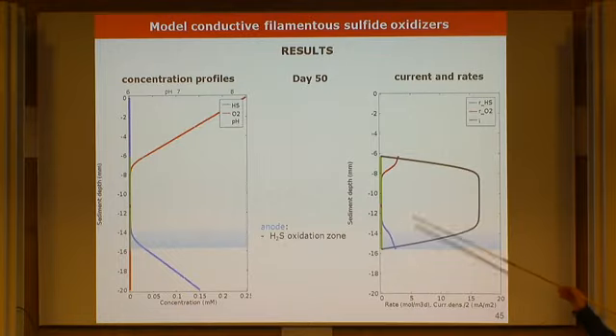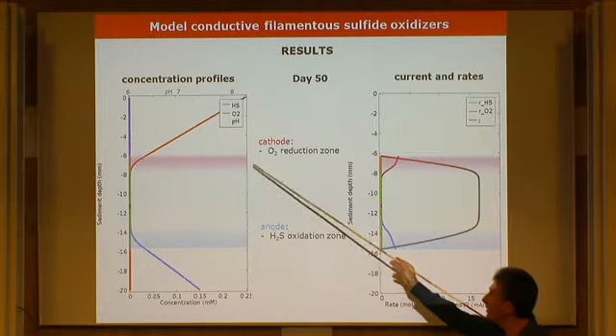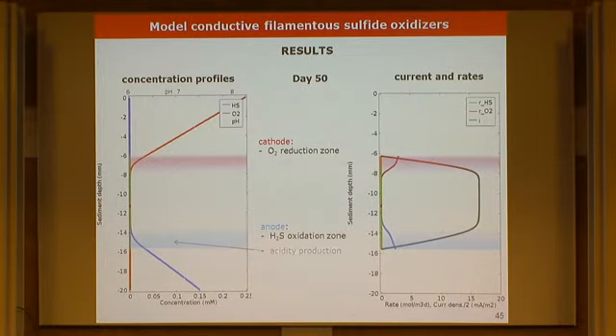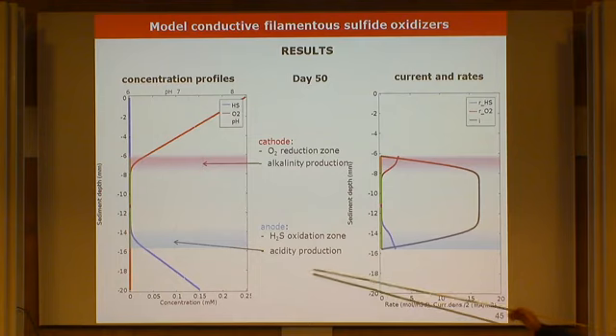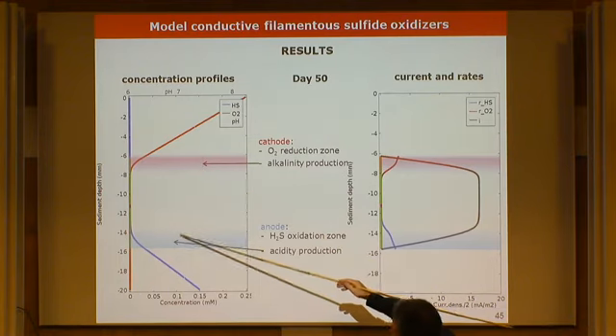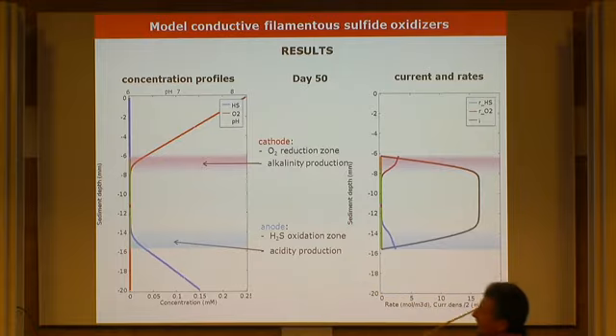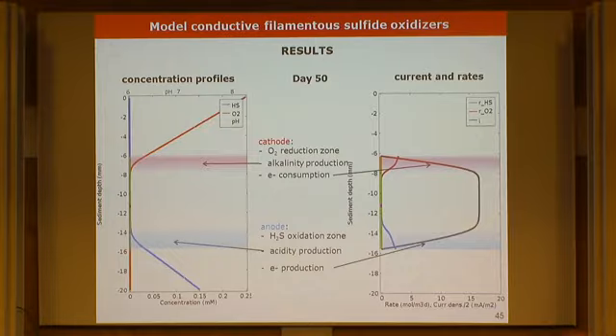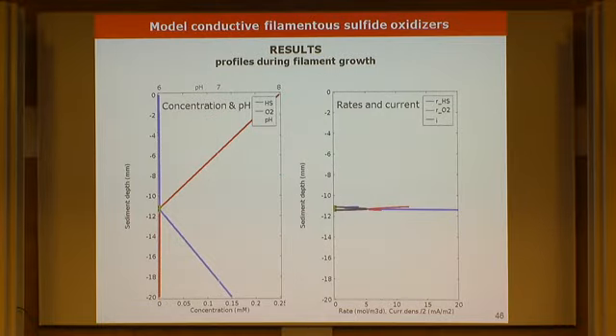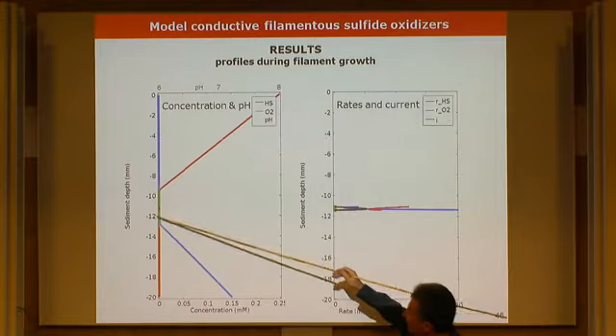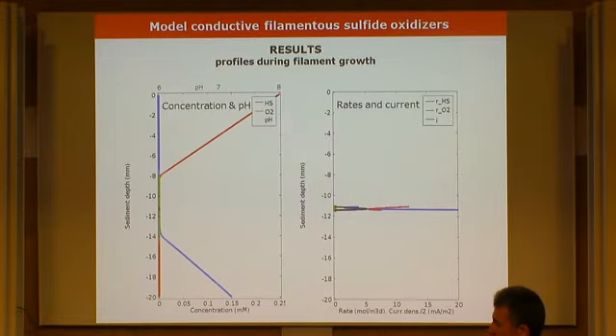We try to put decay as well. Okay, so this is the oxygen reduction zone, the red one, and you have here acidity production. You don't see very well this gray profile. This is the pH calculated, more acidic. On top is more alkaline. Electron consumption here, and this is just conduction, what I told you. And this would be kind of development of these profiles in time.